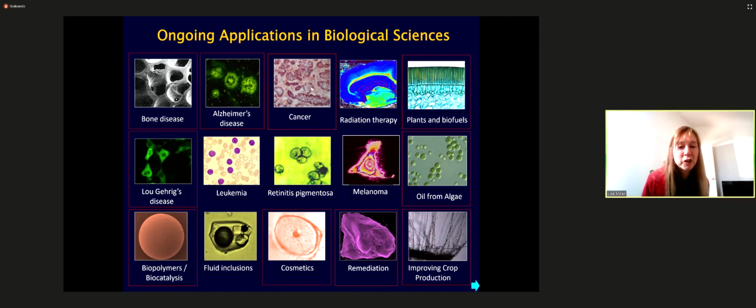The ones that I showed you, those bone samples are all embedded in methyl methacrylate. There's a couple ways of preparing bone samples, but the ones that I showed you were embedded in methyl methacrylate, and we used a microtome to cut them 5 microns thick.